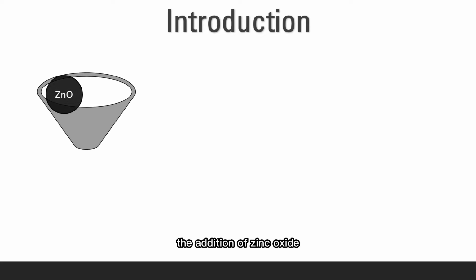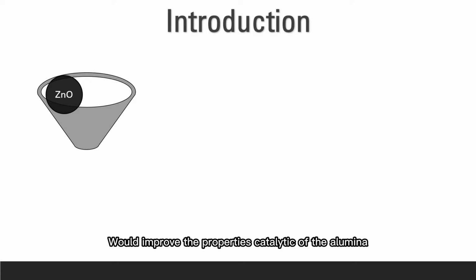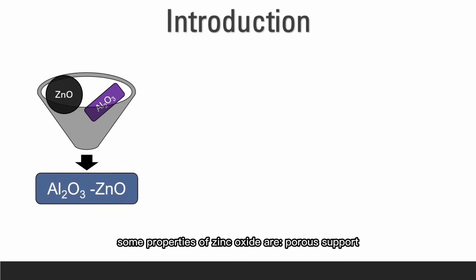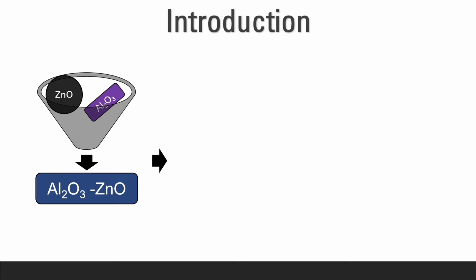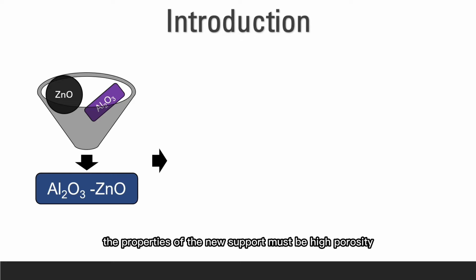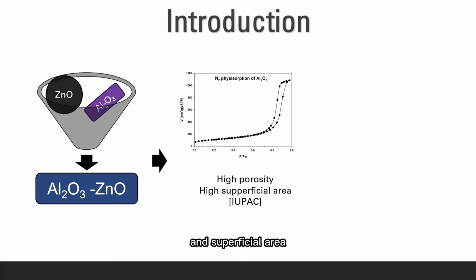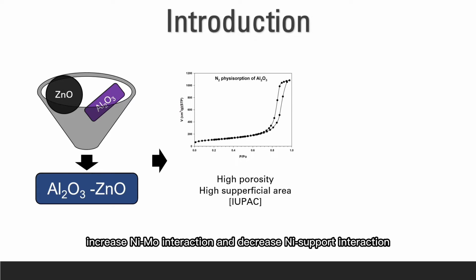The addition of zinc oxide will improve the catalytic properties of the alumina. Some properties of zinc oxide are porous support, mechanical strength, stability of the active phase, biodegradability, low toxicity, and thermal stability. The properties of the new support must be high porosity and superficial area, increase nickel molybdenum interaction, and decrease nickel support interaction.